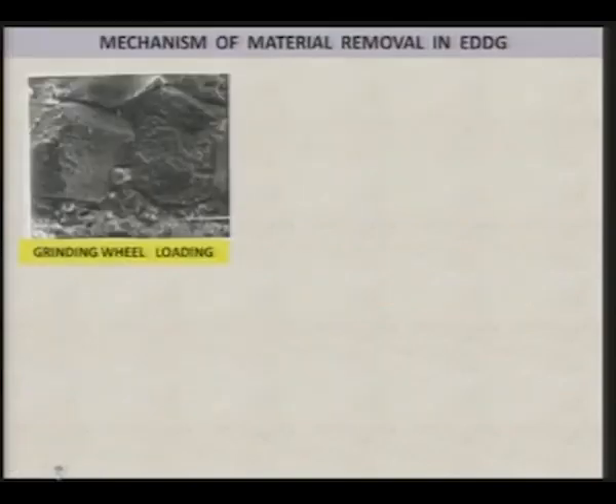Now, I also mentioned wheel loading or clogging. We tried to take some pictures of the wheel loading, and this is the diamond grinding wheel, with the scale shown here. You can clearly see the debris between the abrasive particles, and this debris leads to what is known as wheel loading or clogging of the abrasive particles.